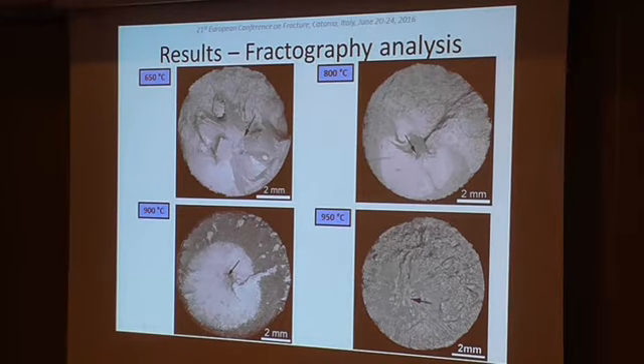Fractographic analysis. I put here examples of fracture surface from each temperature, where you can see distinct changes of appearance of fracture surface. When the temperature is 650, you can see almost brittle-like fracture appearance, which is stage 1 crack propagation. Here on all pictures the initiation sites are highlighted by black arrows, and you can see that with increasing temperature, this mode of crack propagation is changing.